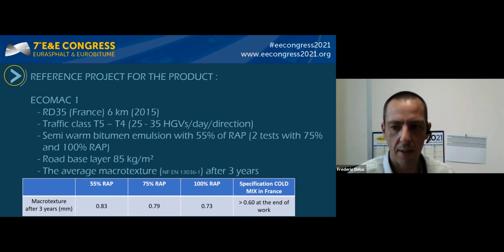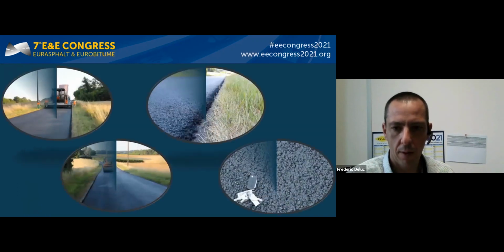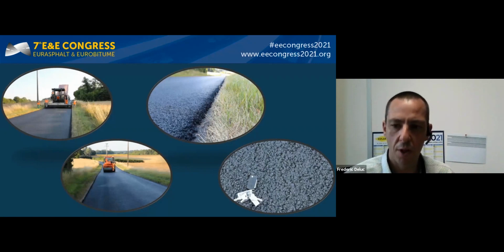The spread rate was 85 kilograms per square meter. Monitoring was conducted for 3 years, and it can be seen on the table below that after this period, the macrotexture was still very good, whatever the RAP content. It should be noted that these values are better than the French specification for emulsion mixes at acceptance. This slide shows the work in question with laying carried out with a paver and a drum roller, and also the appearance of the laid product.